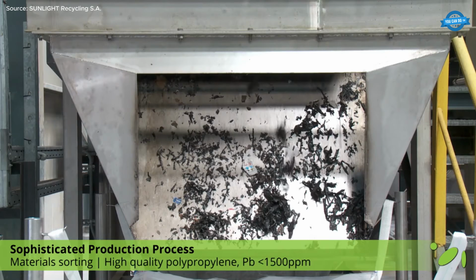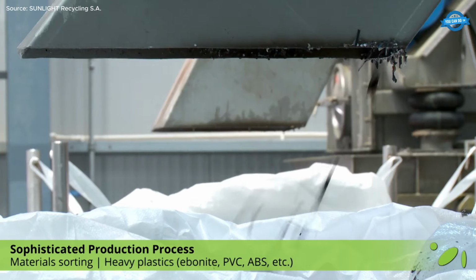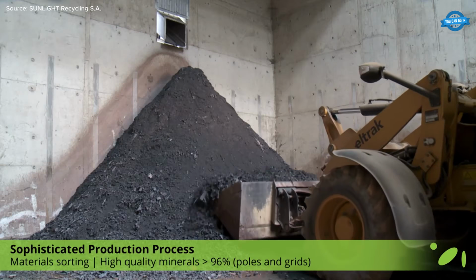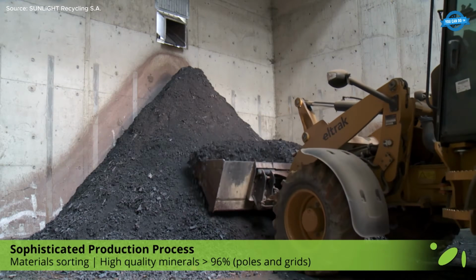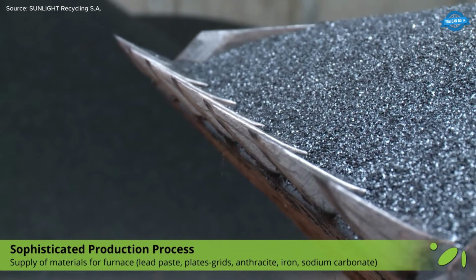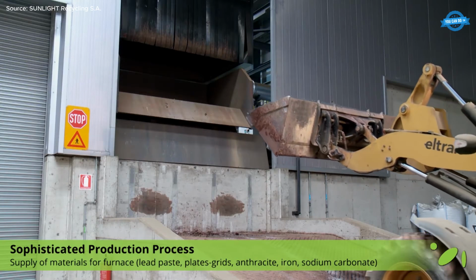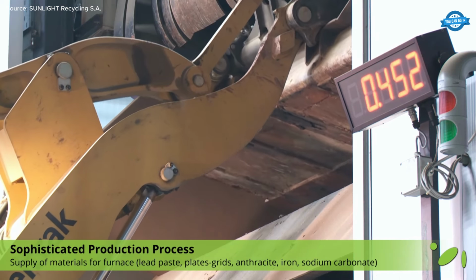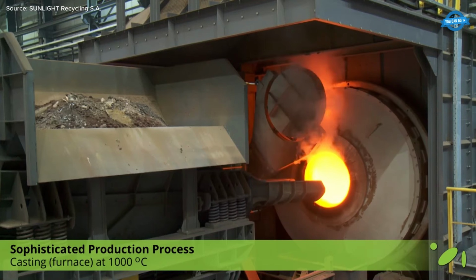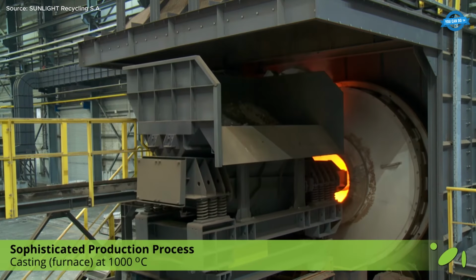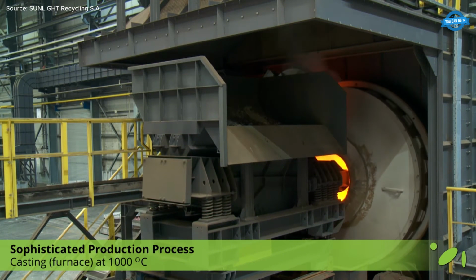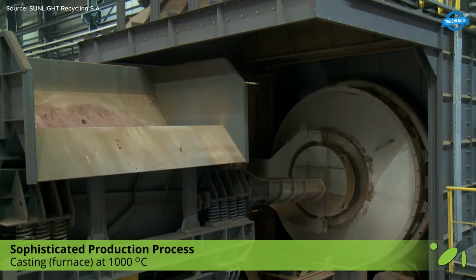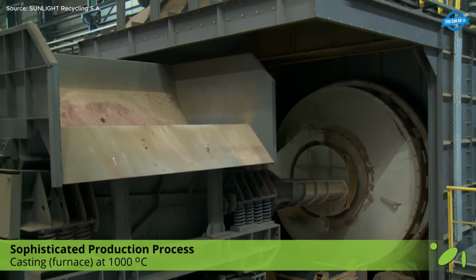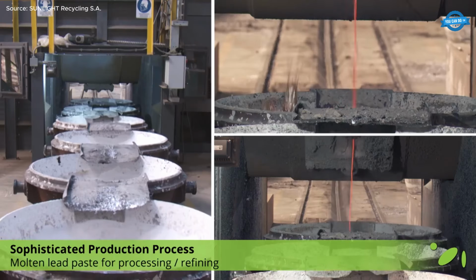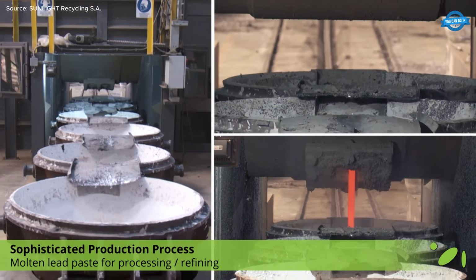Lead paste, plate grids, poles, and auxiliary additives such as anthracite, iron, and sodium carbonate are prepared as furnace feedstock. In the casting furnace operating at approximately 1000 degrees C, metallic lead is liberated, forming a molten phase ready for subsequent refining. The refining line upgrades recovered lead into ultra-high purity ingots, achieving 99.99% pure lead and tailored lead alloys for industrial applications.